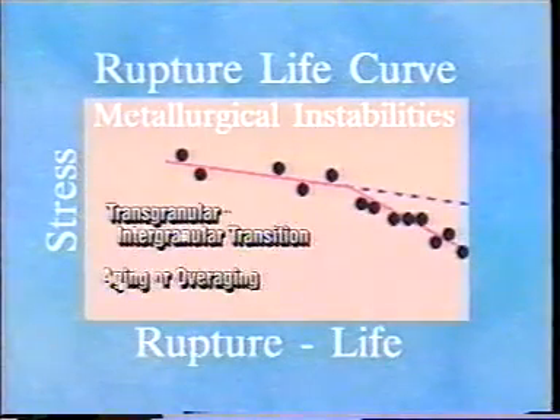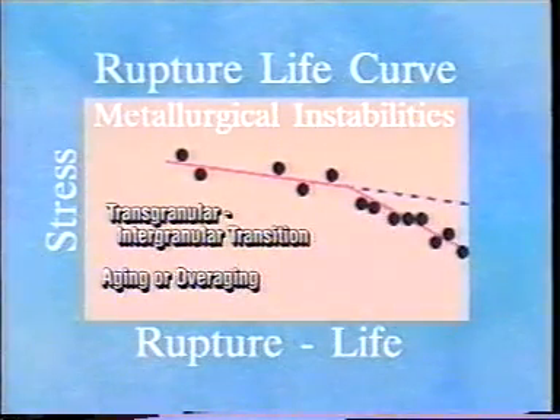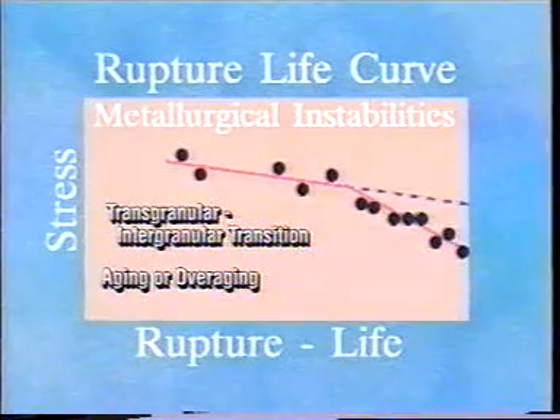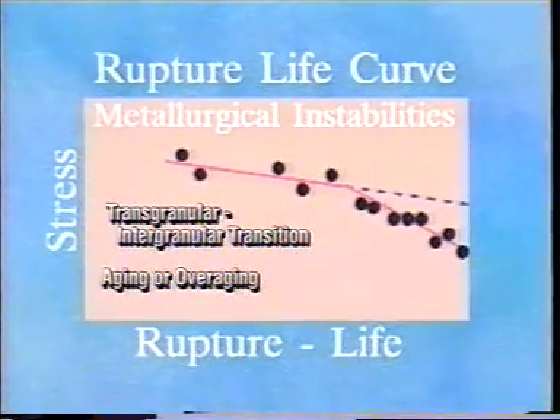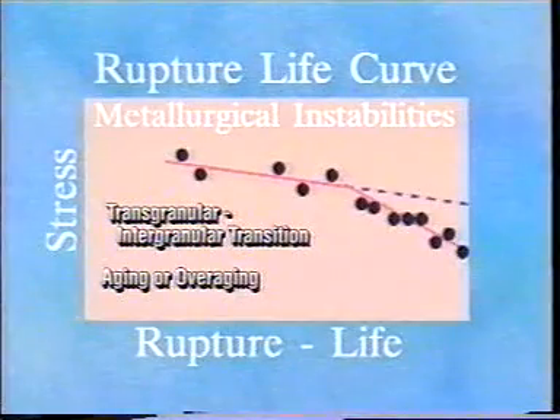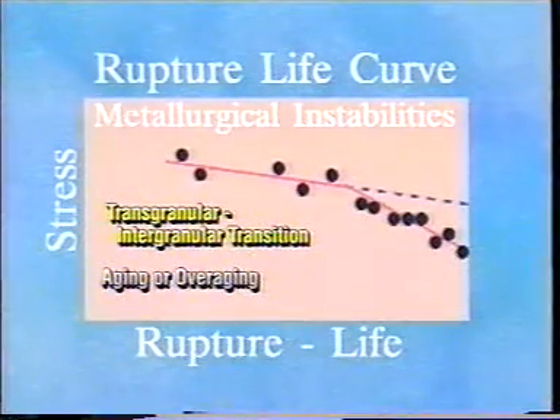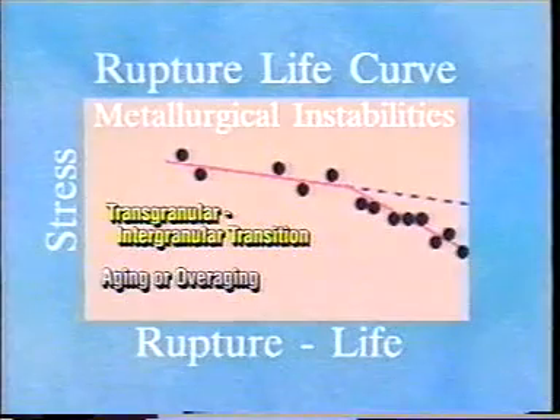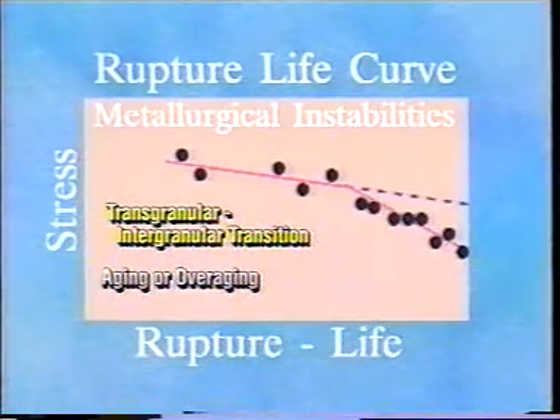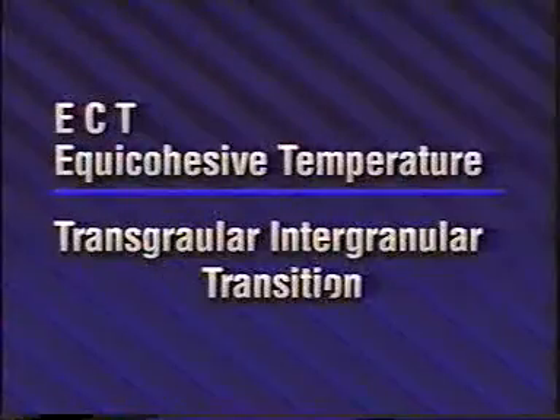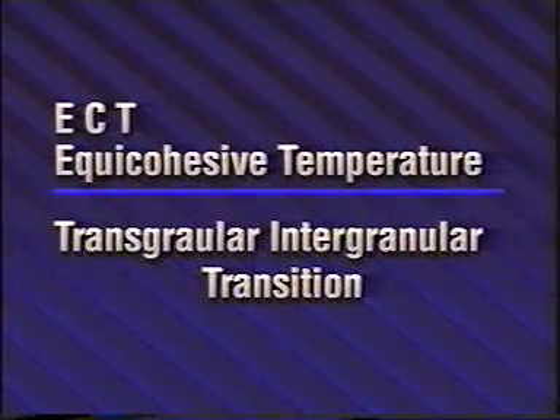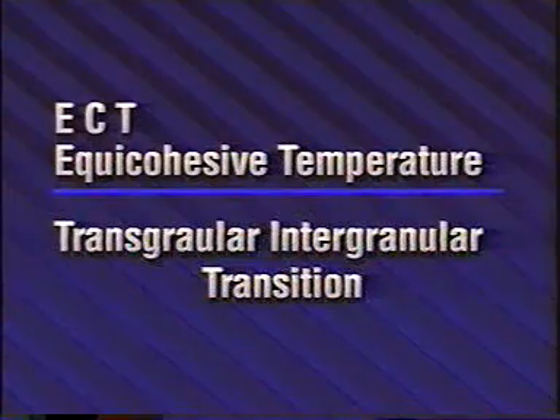Sources of instabilities include transgranular intergranular fracture transition and aging or overaging. This involves precipitation or decomposition of carbides, borides, or nitrides. The principal metallurgical factor in stress rupture behavior is the transition from transgranular fracture to intergranular fracture. The temperature at which the transition occurs is called the equicohesive temperature, or ECT.